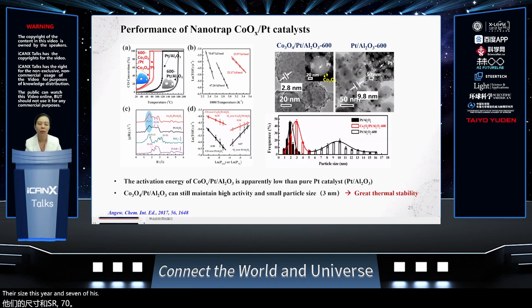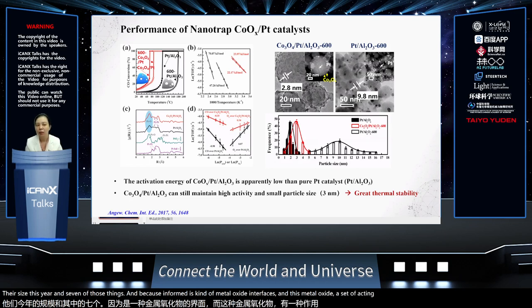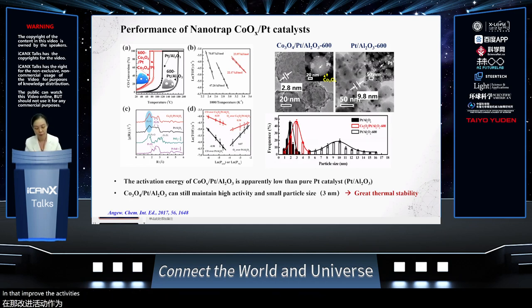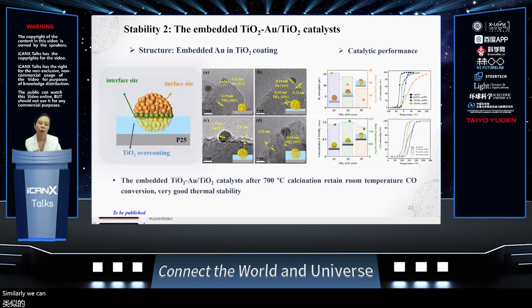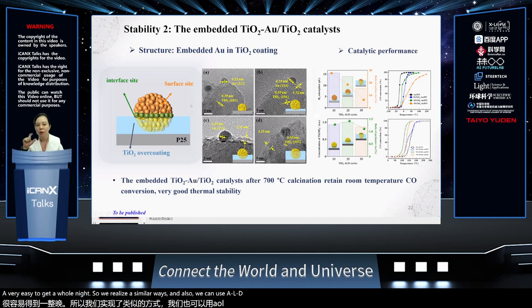The second good thing is that because you form this kind of metal oxide interface, and this metal oxide is sort of active, that improves the activities as well. Similarly, we can run this for another type of metal, like gold, which is a good catalyst but very, very easy to get agglomerated. So we utilize similar ways, and we can also use ALD to control not only the size but also the height, how to confine the metal nanoparticles. And for that, we obtain this kind of gold titanium composite structure.